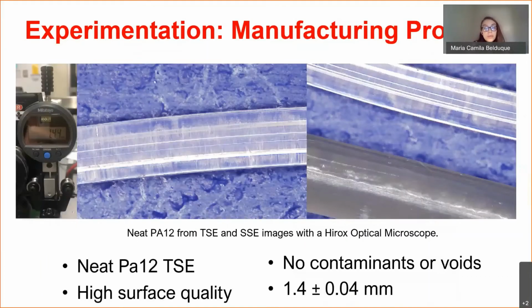So in this picture, we can see the difference between the two neat PA12 filaments. The surface quality of the twin screw extrusion filament is clearly smoother, and there are no voids or contaminants due to the vacuum process. However, it has a smaller diameter, which we measured with a filameasure. And the bright parts that you can see in the image are just a reflection of the light in the lab at that time, but the quality is pretty good.